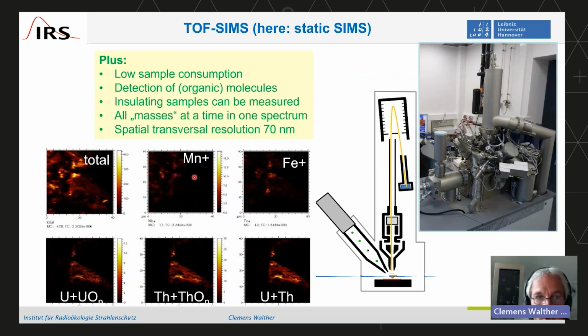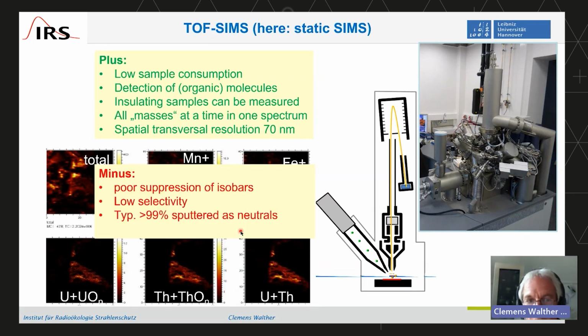Since you can also do imaging, you just scan your primary ion over the probe, and then you can get information on different elements. In this case, that was not nuclear forensics, that was just natural minerals from Afghanistan, where uranium and thorium were present, but it was natural occurrence because we were asked whether it was depleted uranium ammunition, and we came to the conclusion, no, it was not. It was just a natural mineral containing a lot of uranium.